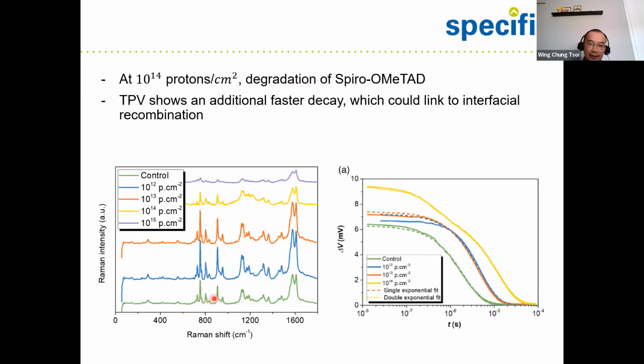This one shows the Raman spectrum. You can see the spectrum of the hole transporting layer is quite similar up to 10 to the power 13 protons per centimeter square, pretty consistent with the good stability at this fluence level. But when you go to higher fluences, you start to see a drop in the intensity, which matches the degradation. So we think it's not the perovskite degrading, which makes it even more interesting, right? Because perovskite is the active layer, so it's more likely due to the organic hole transporting layer.